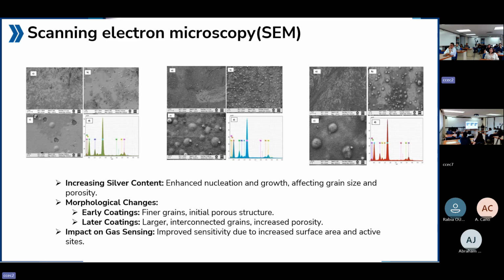Scanning electron microscopic images visually confirm the impact of Ag on the film morphology. Interestingly, we notice that the increase in the addition of Ag layers has enhanced the nucleation and growth, which affected the size and the porosity. For example, early coatings like layer 1 showed finer grains and an initial porous structure, whereas the later coating, especially the 3 layer one, showed interconnected larger grains with a more porous structure than the initial ones. These changes in porous structure and surface area can again affect the properties of the film, which may lead to a change in the gas sensing performance of the films.